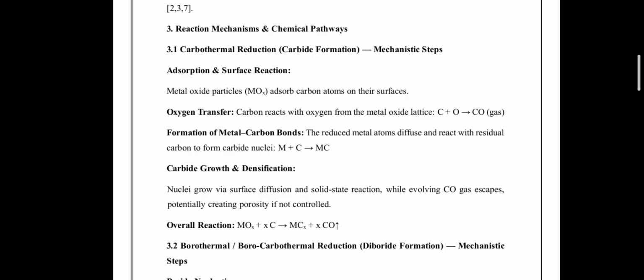First is carbothermal reduction and carbide formation. Carbothermal reduction is a primary synthesis route for transition metal carbides from oxides at ultra high temperature. The process begins with the adsorption of carbon, either solid carbon or carbon derived from precursors, onto the surface of metal oxide particles. At elevated temperature, carbon extracts oxygen from the metal oxide lattice, producing carbon monoxide gas. This removal of oxygen reduces the metal cations, enabling the formation of metal-carbon bonds. The reduced metal atoms then diffuse locally and react with the available carbon to form carbide nuclei.